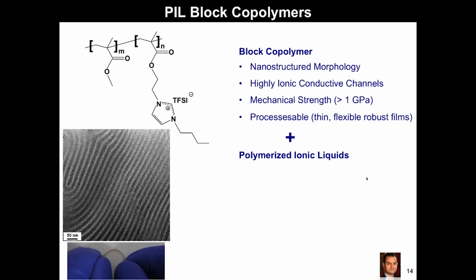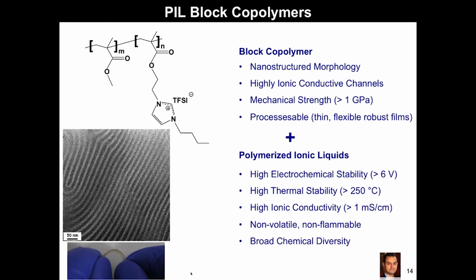So we know block copolymers have great features such as nanostructured morphology, and that can produce high ionic conductivity channels. And then you can also incorporate the orthogonal properties, high mechanical strength for applications such as batteries and fuel cells, and be able to make very processable films that could be molded how you like for that application. However, within the microdomains, you are putting in polymerized ionic liquids. And the attractive feature there, particularly for applications such as batteries, is that you're incorporating chemistry that has a very high electrochemical stability or high electrochemical window.